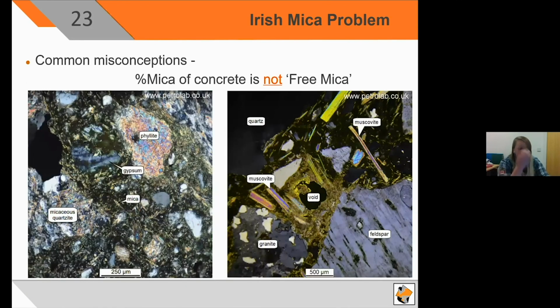So a common misconception, which we have seen a couple of times now: the percent of mica of the total concrete is not the percent of free mica. So on the left, you have a typical phyllite aggregate. You can see the mica in the binder with the high colour all distributed throughout the binder, whereas the one on the right is our primary China clay waste aggregate, which has literally muscovite everywhere. As you can see, there's literally so much mica in there.